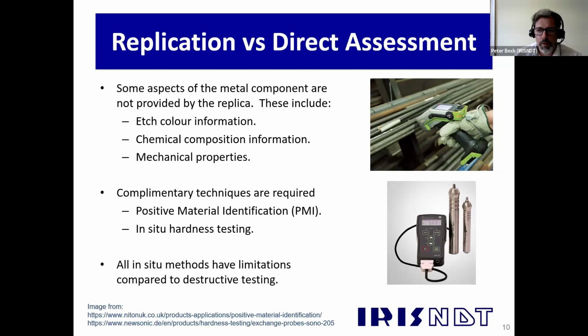The chemical composition obviously isn't transferred. It's an acetate replica. It's not the metal itself. And for that, we would use positive material identification. So you can see in the top image, we have an XRF gun. So X-rays are fired at the material. The incoming X-rays are assessed and identify the different elements in it. Typically, this is for steels and stainless steels. Other materials can be done, but we typically stick to steels and stainless steels.